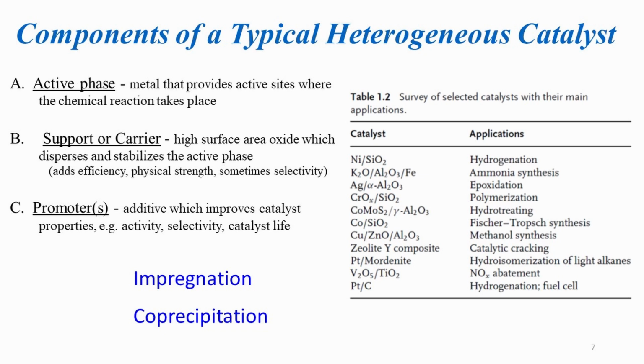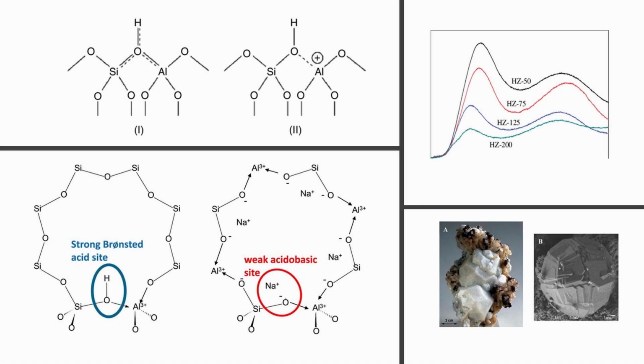The nature of the active site has a direct effect on the activity and selectivity and will be determined by atomic structure. For acid sites in the zeolites, the nature and geometry of the heteroatoms, for example aluminum or silicon, will determine acid strength. The density of the acid sites, which is important first of all for activity, may be controlled by the metal loading or by the alumina-silica ratio of the zeolites.